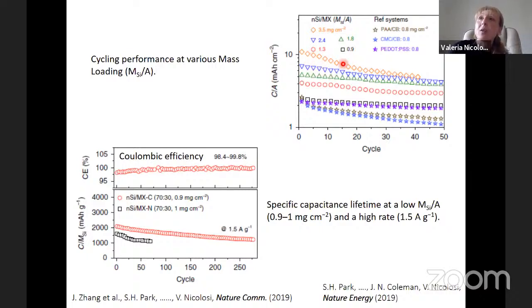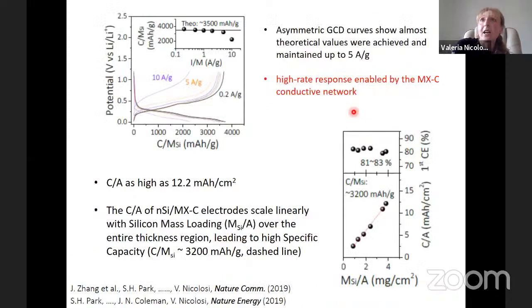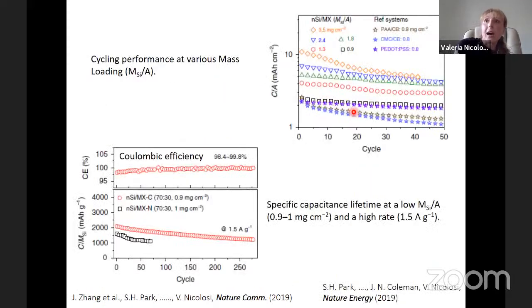Here is a comparison between our devices at different mass loadings and some reference materials. So again, we overcome any limit that has been reached in the literature so far. And this is actually something very, very important to stress. And then the specific capacity, lifetime, at low mass loading and high rate was outstanding.